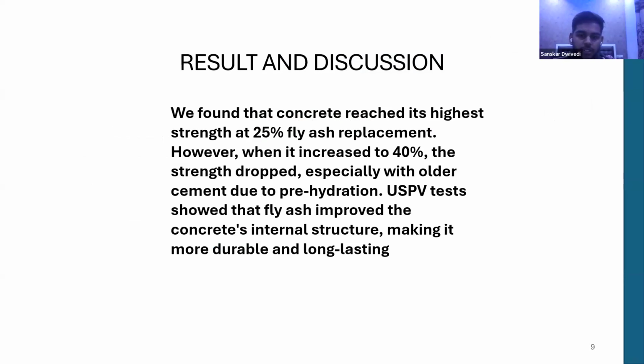And for result and discussion, we have already found that if we replace 25% of cement by fly ash, we can get the highest strength of the concrete. But if we use 40% of the fly ash, the strength drops. So these are the tests I have already explained, and the USPV test shows the increased strength of fly ash.